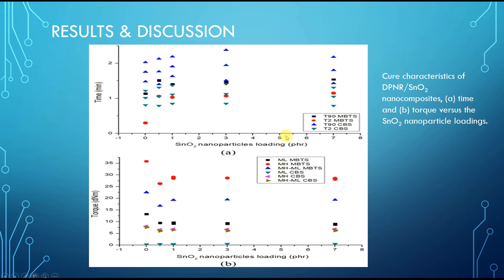When we underwent the rheometer study, it shows that as tin dioxide loading increases, it shows a pattern which decreases the maximum torque and also minimum torque. This shows that the tin dioxide filler can act as a plasticizer.